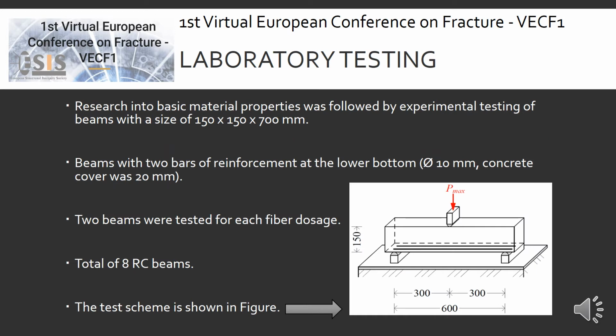Research into basic material properties was followed by experimental testing of beams with a size of 150 by 150 by 700 mm. Beams with 2 bars of reinforcement at the bottom, diameter 10 mm, and the concrete cover was 20 mm. 2 beams were tested for each fiber dosage, a total of 8 reinforced concrete beams. The test scheme is shown in the figure.